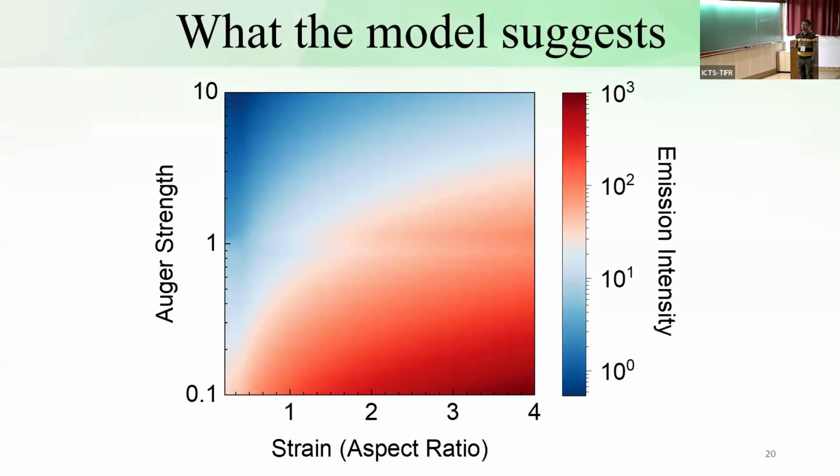We did a bunch of calculations, which I am not showing here, but there is another problem here, by the way. It's good to have a lot of excitons here, because it acts like a reservoir, and your reservoir ideally should be an infinite supplier, right? But the fact that you are forcing many excitons to come close by, there is a very strong exciton annihilation that happens, and this is just the Auger process, right? Because of that, you tend to reduce this exciton density right on top of the pillar, and that's a bad thing.